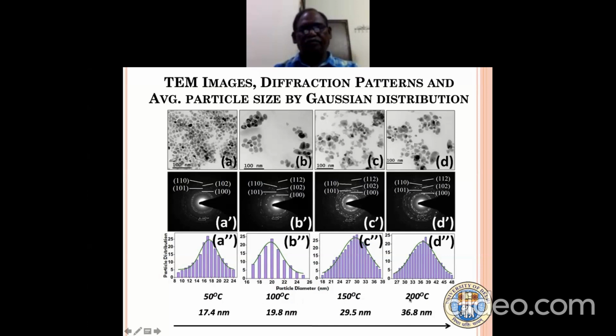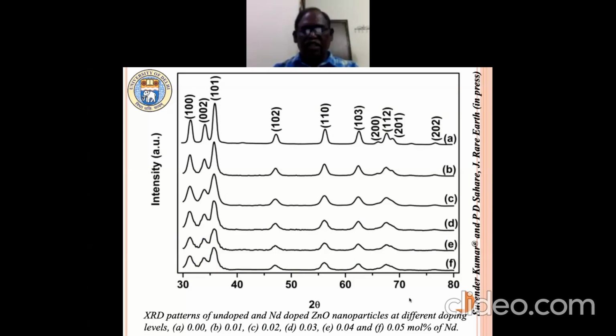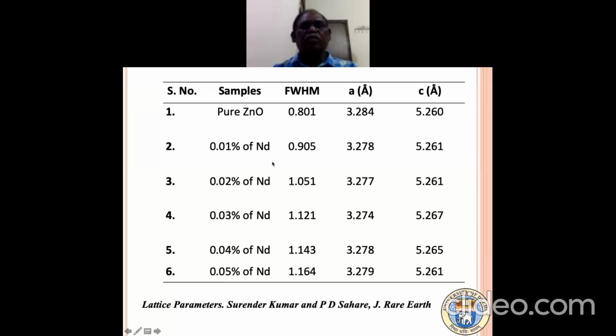And this shows the XRD of different samples. Also, if you change the neodymium concentration over here, there is a little shift in the XRD because of some stress formed by more and more impurity in the material. And therefore, these lattice parameters also change.